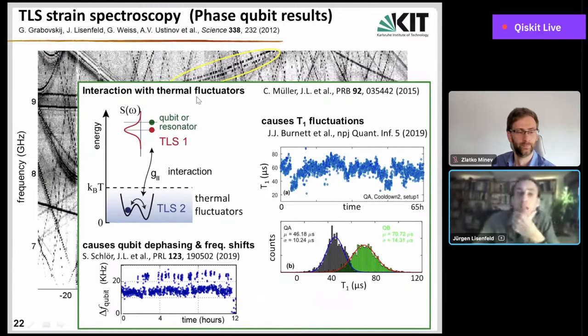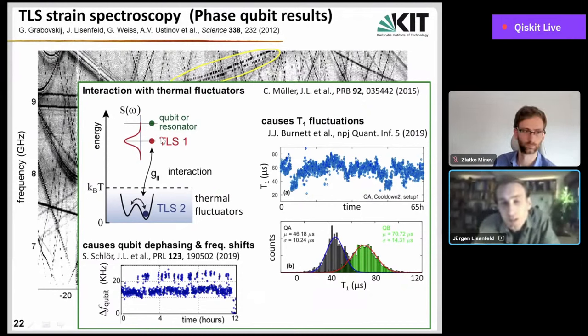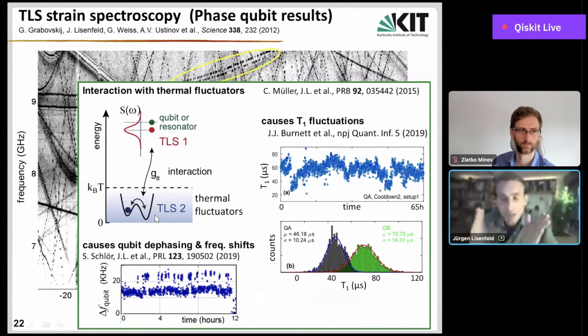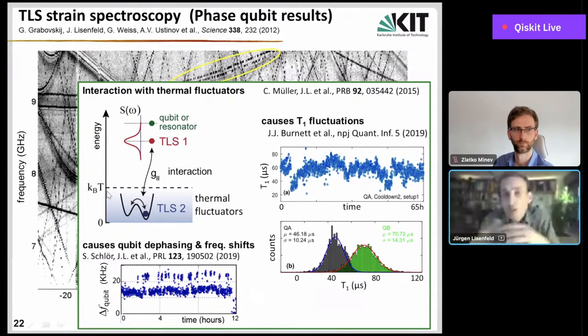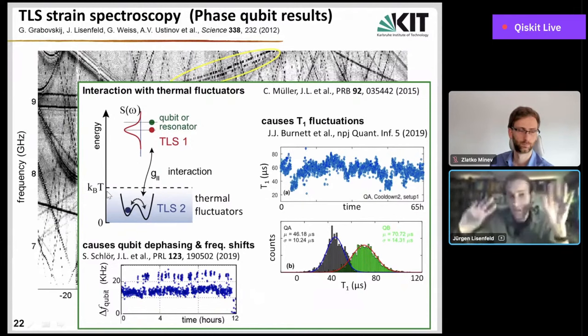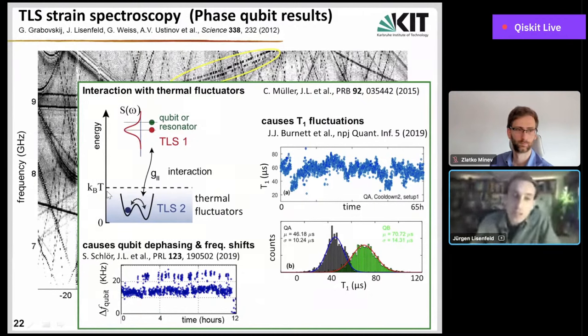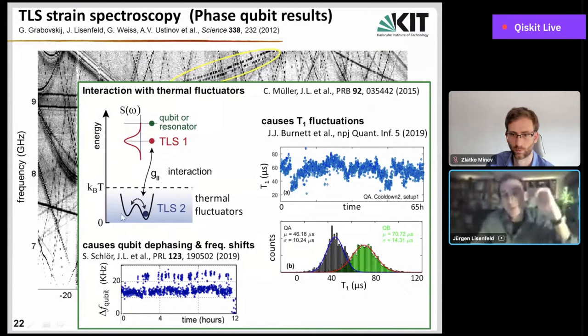And it is explained by the following: this defect that we can see here has a rather high frequency, so close to the qubit that you can actually measure it using the qubit. Such a high frequency defect may be coupled to a low frequency defect, which may be physically the same thing. It just has an excitation energy below the thermal energy, kBT, so that you can treat it as a random, classical thermal fluctuator, just switching randomly between its two states without much coherence involved. But if this kind of thermal fluctuator is able to interact using this longitudinal coupling with this high frequency defect, then this high frequency defect would just have a changing resonance frequency, which follows the state of this thermal fluctuator here. And this is exactly what you can see here.